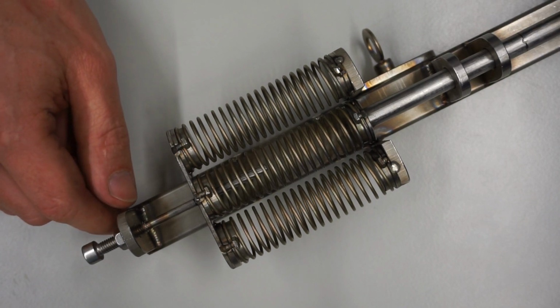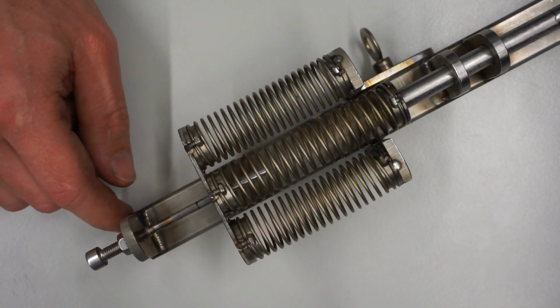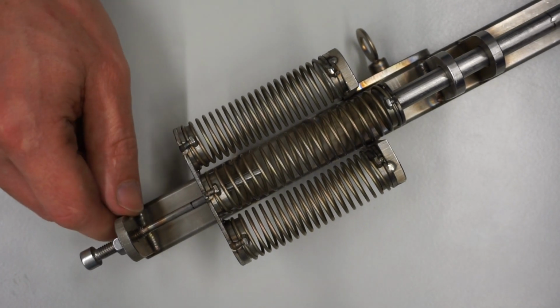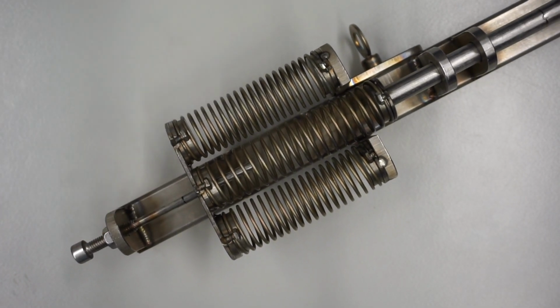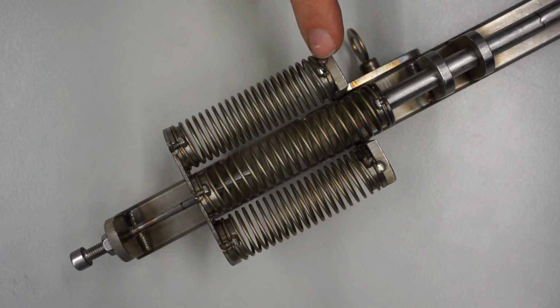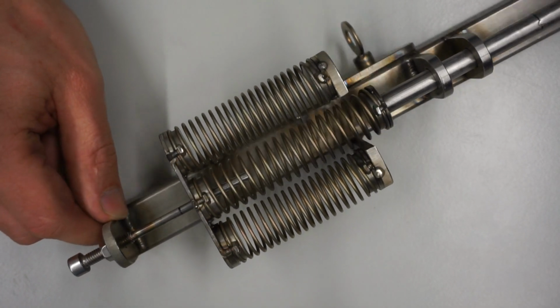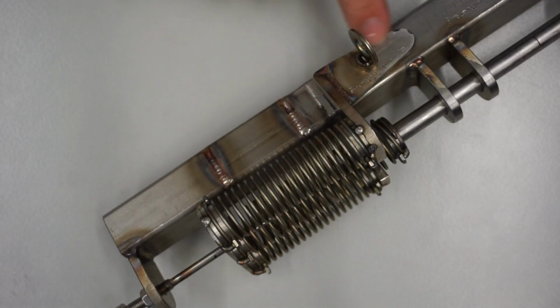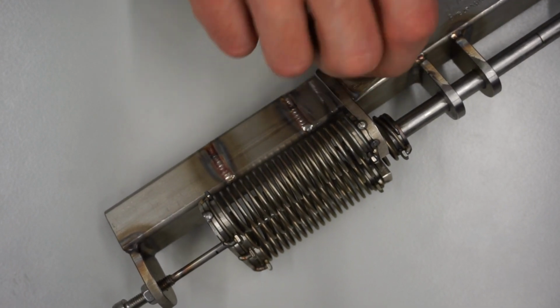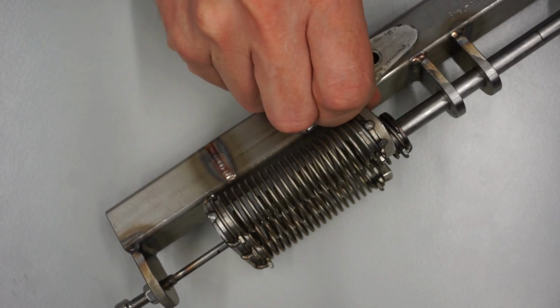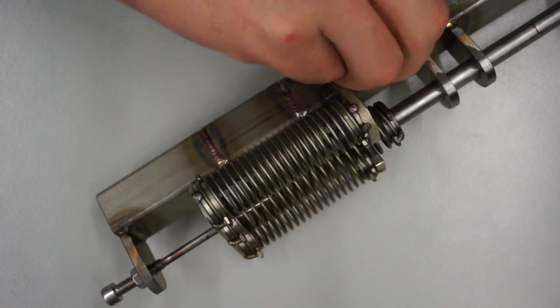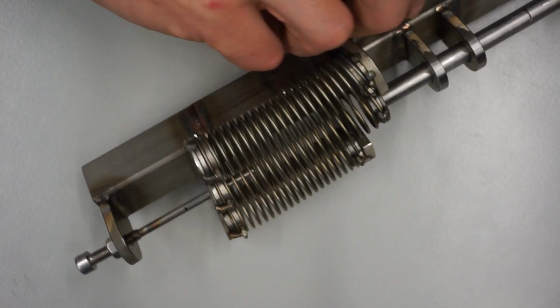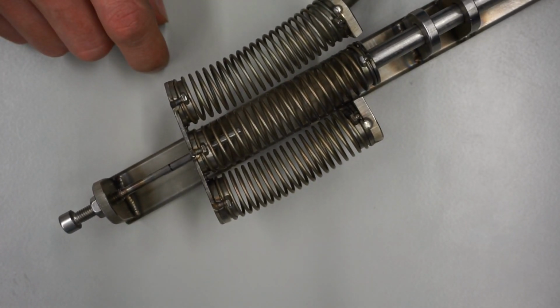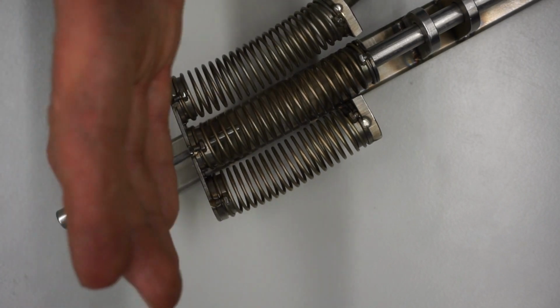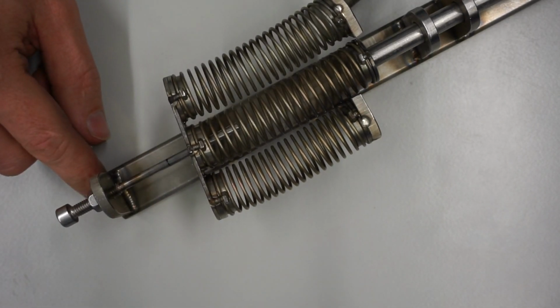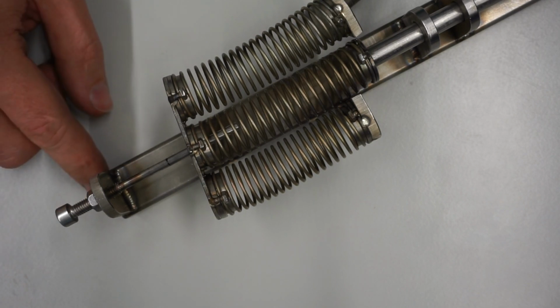Recall that our welded workpieces are in certain areas loaded with residual stresses, for example like the contraption here. If we machine away material which is loaded with residual stresses, let's assume we machine away part of this bar here, see what happens. I can take off the holder of the spring here. There's a pin in there. The bar experiences springing back distortion because the remaining residual stresses must find a new balance again. This is only possible if the workpiece distorts.